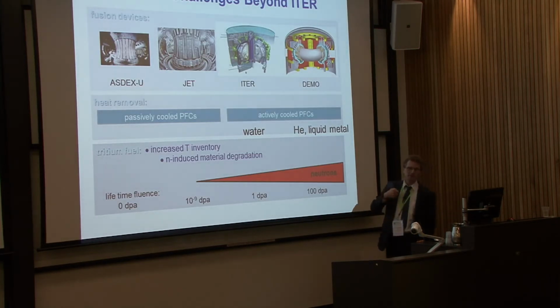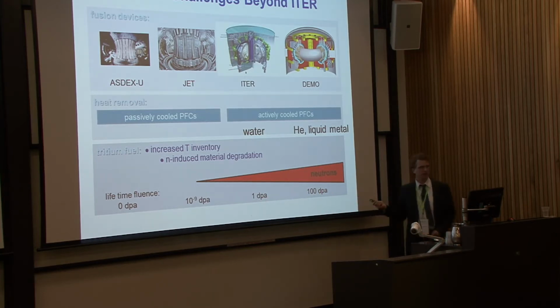If I look at materials challenges beyond ITER, going ahead, well, this is the neutron fluence. So for JET, it's basically 0. For ITER, it's 1 dpa, so this is displacements per atom of the first wall. But going to DEMO, it's enormous. It's 100 displacements per atom. So that's a very large amount of damage that the first wall has to be able to withstand for a power reactor.